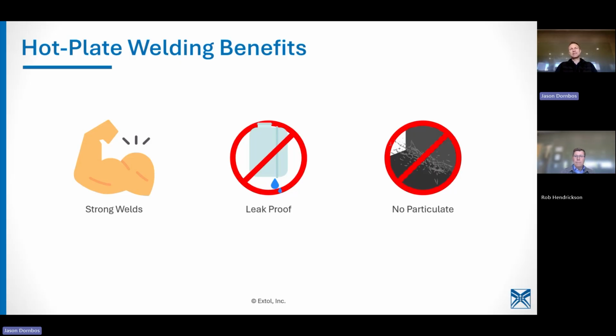There are other processes that join plastic parts where, usually when you're having a friction-based process, that can generate particulate, which means there's plastic fibers and loose particulate coming off of the weld joint. Not an issue for some applications, but in some, you would need a cleaner assembly, and particulate's a bad thing. So hot plate welding doesn't have any particulate. And generally speaking, because of that molecular exchange that's happening, it's really the strongest weld you can get. Yeah, it really is. It's a very strong, robust weld.